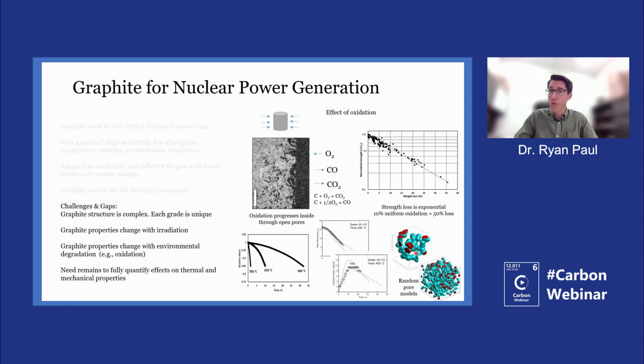And so recently, some work that I've been involved in has been looking at how we can better understand the pore structure effects. As was suggested on the last slide, different pore structures are formed by different grain sizes and forming conditions. And so we need to understand how that is going to lead to these strength losses. And it's not just about strength, it's about the Young's modulus, the thermal expansion coefficient, like we showed on the last slide, thermal conductivity. Many properties are going to change with the radiation and oxidation, and those need to be better understood. There are no standards for studying all of these, and so there really is an urgent need there.